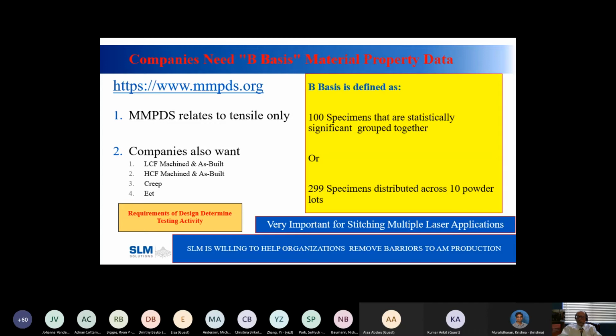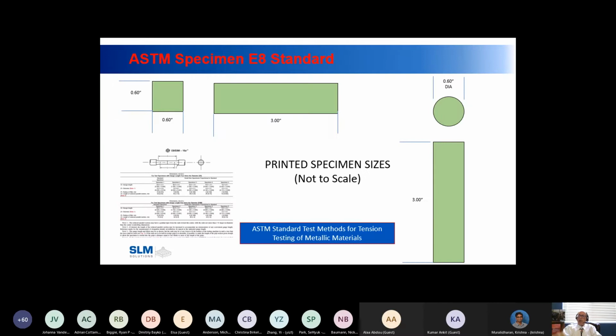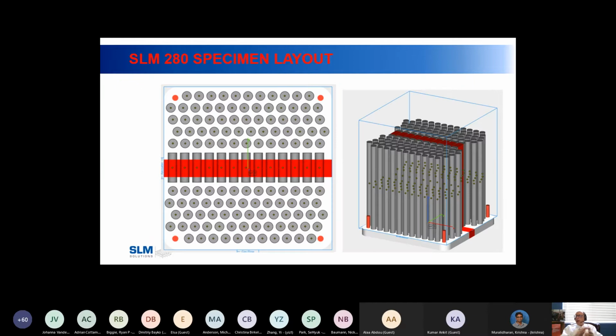All of this data has to be generated, and that creates a real problem because it's extremely expensive. You do it to a standard, and the standard for tensile that I use, ASTM specimen E8. So you print a specimen that is basically 0.60 inch square or diameter, and they're 3 inches long. And out of that, you can machine an E8 standard. And to get the exact dimensions of an E8 standard, you're going to have to get that off of ASTM. I'm not going to give that to you here.